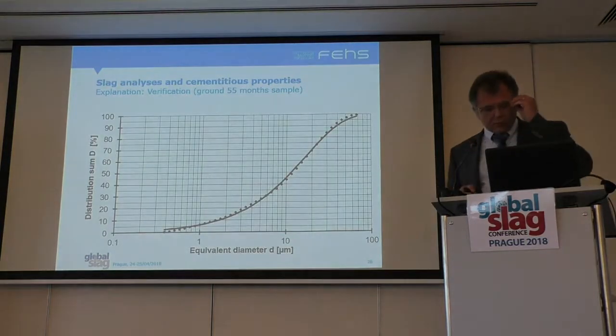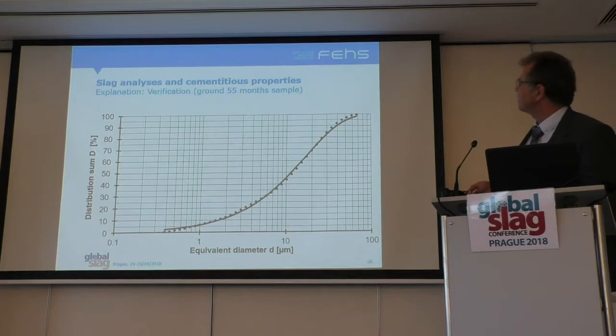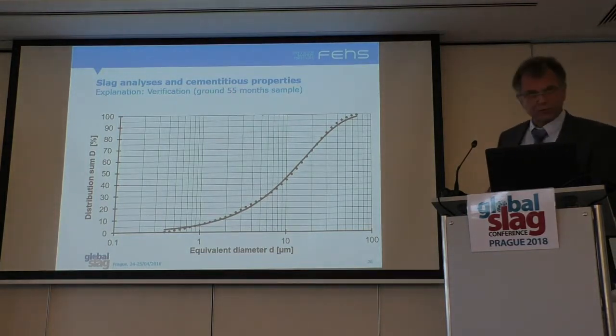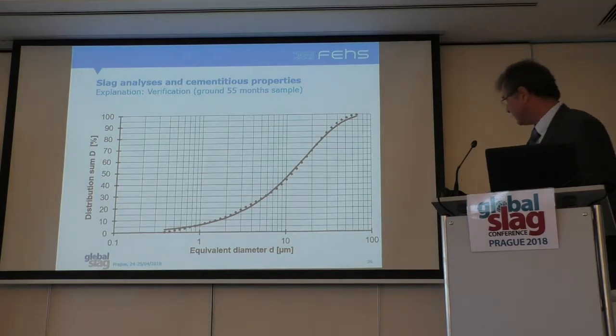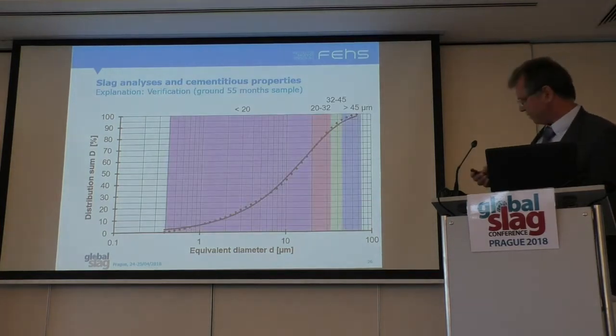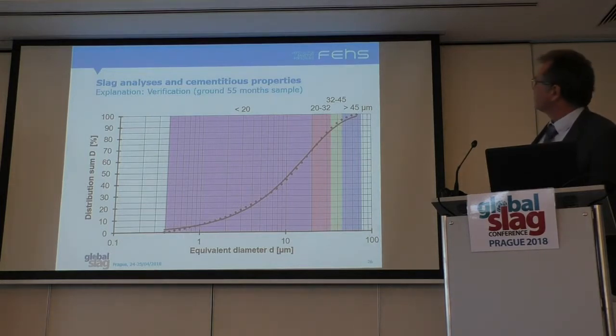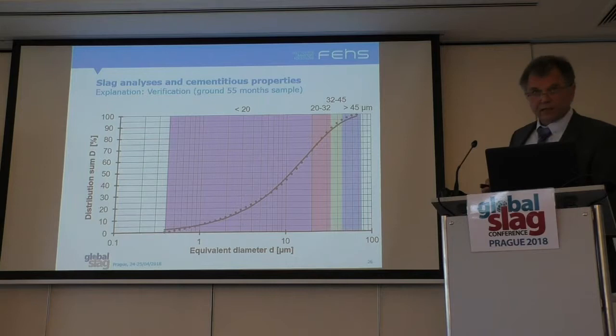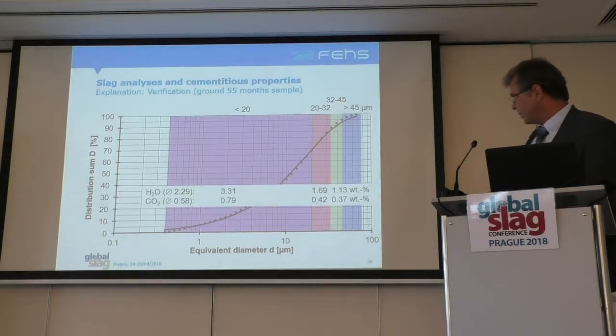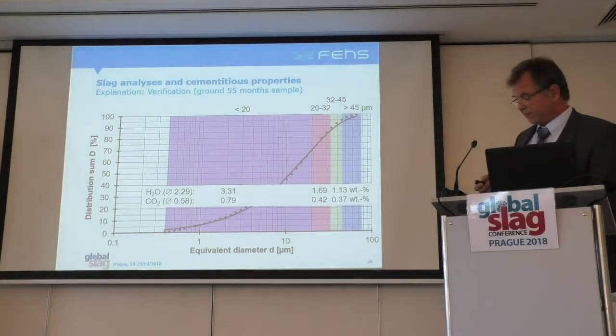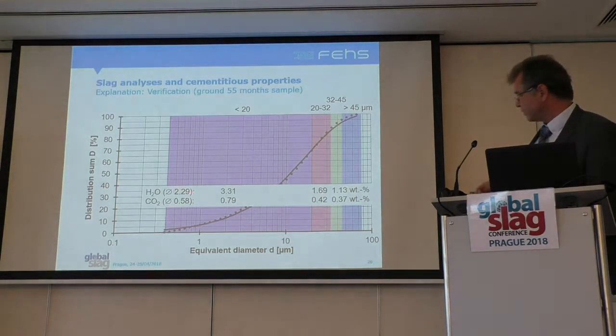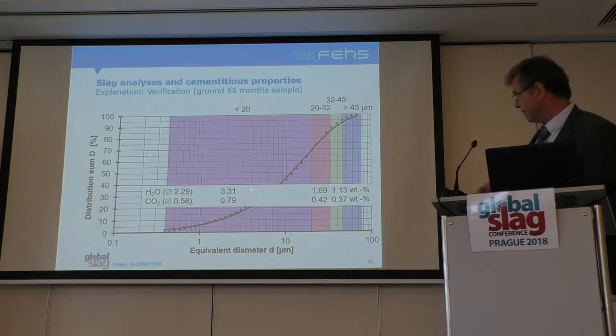So, what we did, we separated the ground GBS, the GBS which was stored for 55 months. We separated in different fractions, and the smallest sieve which we have is 20 microns. And we analyzed separately chemical bound water and CO2. And, surprise, if you have finer material, the chemical bound water content is higher, also CO2.